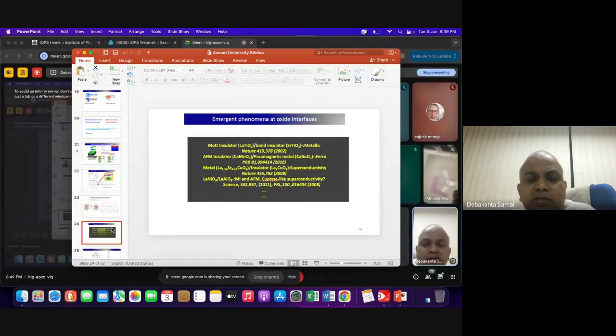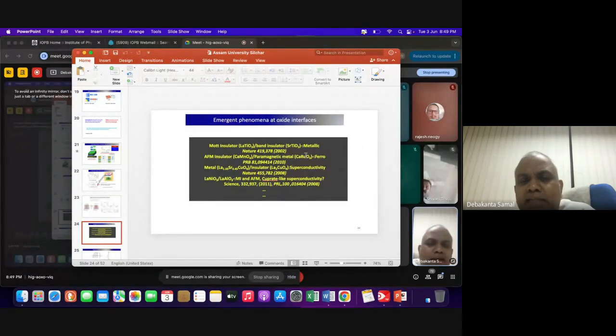Unfortunately, if you look at this Nature paper from the Stanford group, by designing this quantum material heterostructure, layer by layer, playing Lego, they could show that it is not only copper-based systems; they found superconductivity in nickel-based systems. And there is a lot of research going on now for the last maybe 5-7 years. This work started in 2019. From 2019 to 2025, there have been many papers. People are really trying to see whether high TC superconductivity can extend beyond the cuprates, the copper oxide system, which have been studied since its discovery.